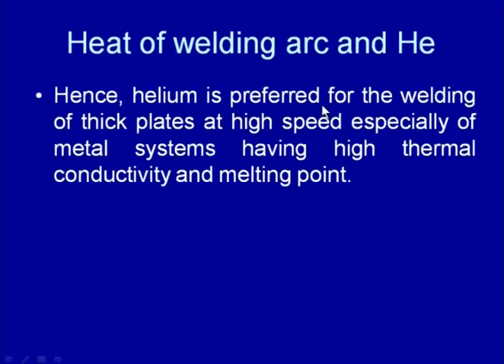So, we will see further details of the difference in the effect of the type of shielding gas on the welding performance of the GTAW process. So, helium is preferred for welding of thick plates at high speed, especially of metal systems having high thermal conductivity and high melting point, because helium helps in generating more heat during the welding, which permits melting at a high rate and with deeper penetration.